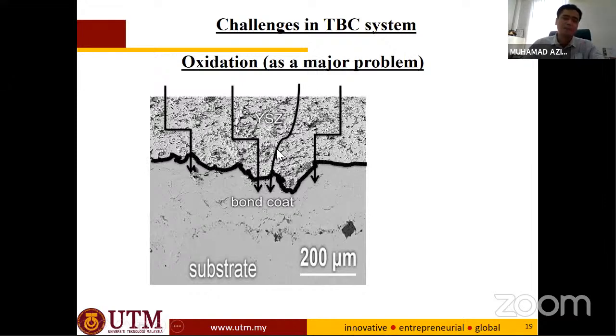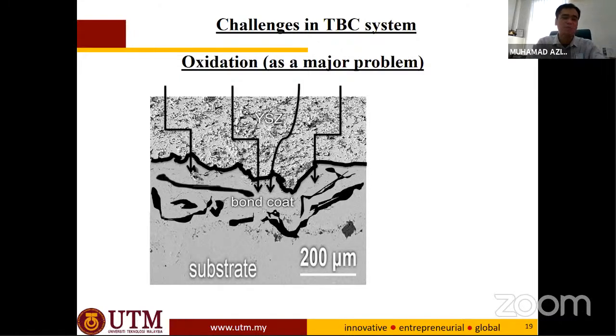The penetration of oxygen: if this ceramic is porous, oxygen can penetrate and go to the bond coat, and then the bond coat becomes oxidized. So what actually happens is we create another thermally grown oxide. You can see here, it is like a barrier. This thermally grown oxide is basically alumina. It is beneficial if you can have a thin thermally grown oxide here, but if it is thick, it is very detrimental.